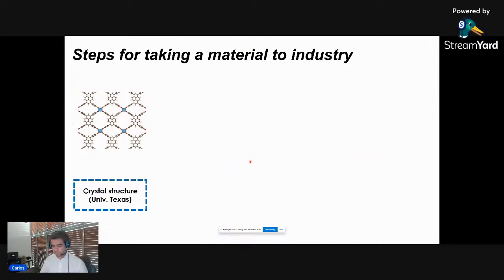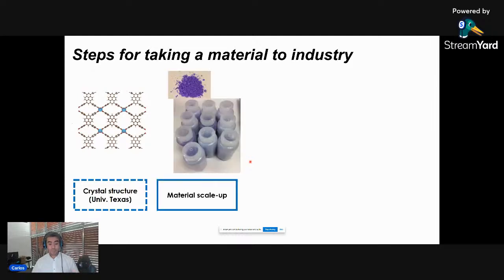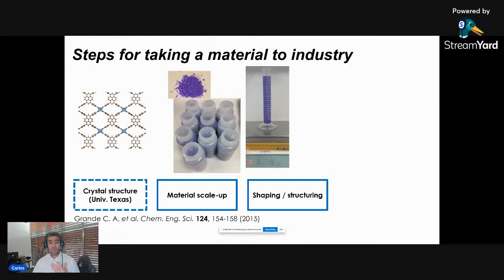In the case of Arvind, for example, with CALF20, and in other cases, we've been trying to do the same. You start with a crystal, you characterize the isotherms, you characterize the diffusion, and after a certain point you have to scale it up. Whether you do it continuously, in batch, or in parallel batch, that's another story. But until that point, you only have a lot of material. You still cannot use it industrially. For that, you have to shape it.